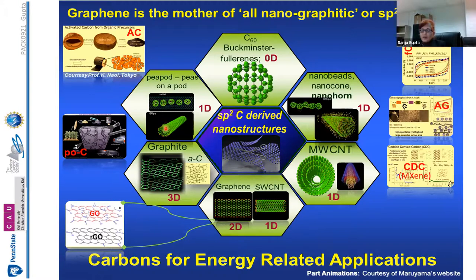In the context of the present talk, the activated carbon, which we call AC in short, was the first carbon capacitor or electrochemical supercapacitor, and it came in fact from Japan back in 1971, which I'm going to show you more about. Then there's porous carbon, because everybody started to make porous carbon, porosity was important, and you will see further on why. Then we have classic graphene, but there are other variants of graphene, like GO, graphene oxide, or reduced graphene oxide, because they have what we call oxygen functionality, either on the basal plane or in the edge plane sites.